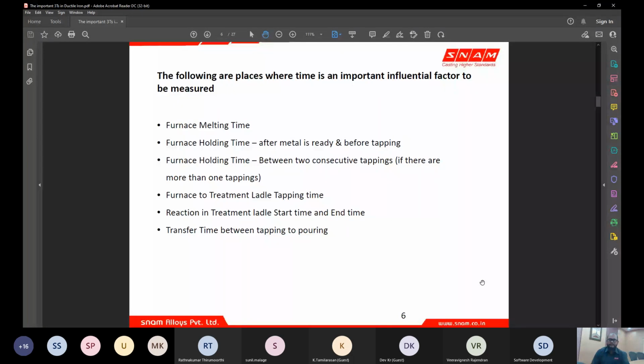Tapping plays a major role, and it is one of the difficult processes being handled in foundries, where tapping and treatment have a lot of violence coming up. During the violence, the operator or the person who is tapping will not be able to view the ladle properly and tap continuously, so there can be a possibility of intermittent tapping. So when your tapping time is longer, that means instead of tapping 500 kg of metal in 30 seconds, you tap 500 kg of metal in 40 seconds or 50 seconds.